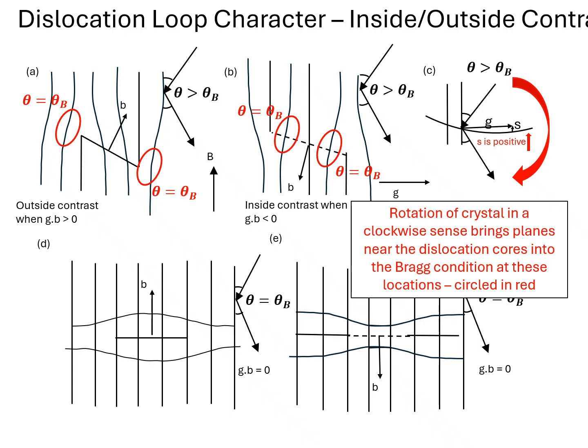So that you can see how, in this case, for this setup, when the crystal rotates, shown by this red arrow here, what actually happens is that you reduce the distance between what would be the diffracting vector and the Ewald sphere. The plane is brought into the Bragg condition. You're basically rotating this G vector so that it comes into contact with the Ewald sphere and gives strong diffraction.